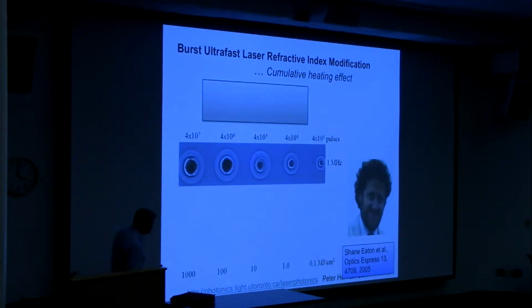All right, so I'm going to just move back to waveguides and mention this work that was done by Shane Eaton, who's now in Milan, a professor there. And we are showing the effect of heat accumulation in waveguide writing. But here, this is a static exposure where 4,000 laser pulses were applied here at 1 megahertz. And then we increased it by 10,000 times, so this is 40 million pulses. And you can see that there's maybe a doubling of the size with an increase of number of pulses by multiple orders of magnitude. So it's not a big change with huge changes in exposure, right? So 4,000 to 40 million pulses.